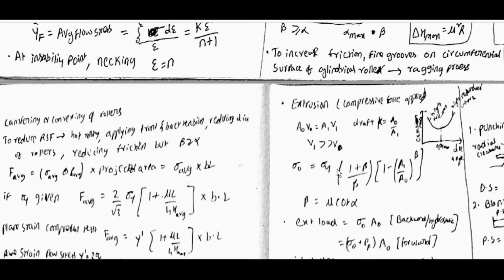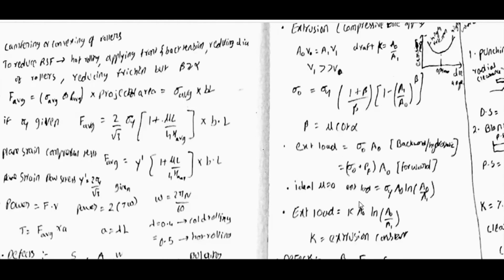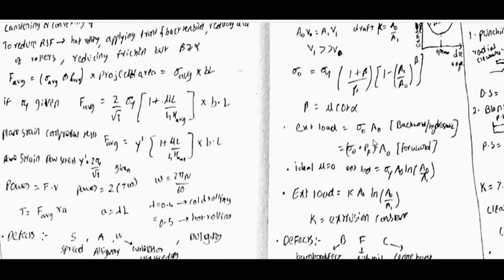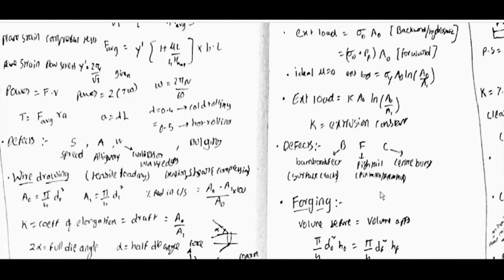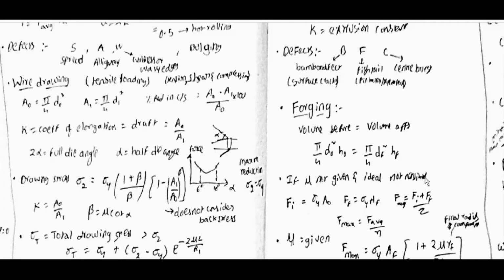Sigma naught is equal to sigma y into 1 plus beta by beta into 1 minus A1 by A0 whole power beta. Beta is equal to mu cot alpha. External load is equal to sigma naught into A0. For backward or hydrostatic extrusion, it is sigma naught plus pf into A0 for forward. Ideal, mu is equal to 0, external load is equal to sigma y A0 ln of A0 by A1. External load is equal to K A0 ln of A0 by A1, K is the extrusion constant. Defects: BFC, bamboo defect, surface cracks, fish tail, pinholes or surface porosity, surface defects, center burst.